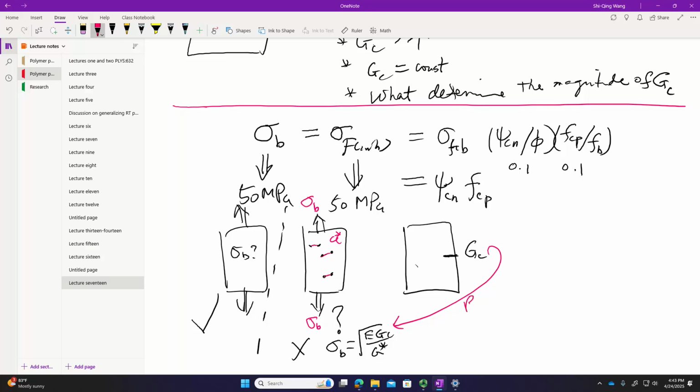I already labored here because Barry is the first one to take a PMMA and make a measurement. Lo and behold, he did find that Griffith's law works, which says nothing about whether there should be flaws for this cut-free sample. But that's the spirit. You use this GC, come back, try to predict a cut-free sample, or explain why the strength is 50. And the way you explain the strength 50 must involve speculating about the size of the flaw, by definition, yeah?